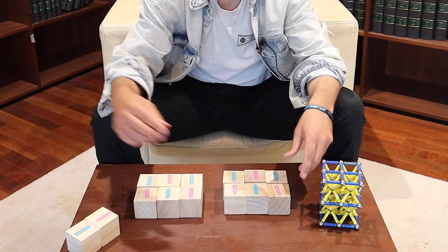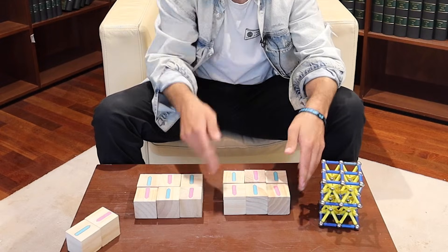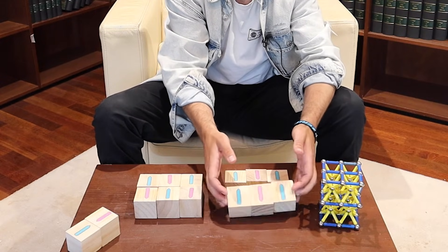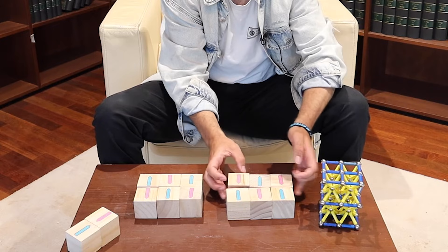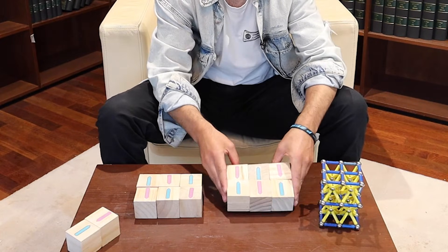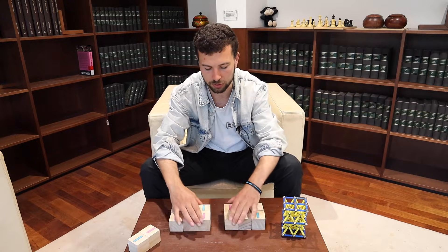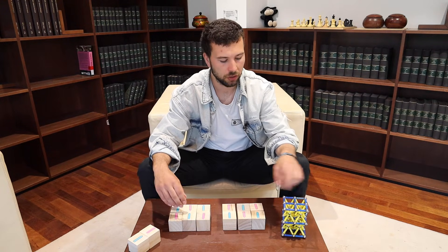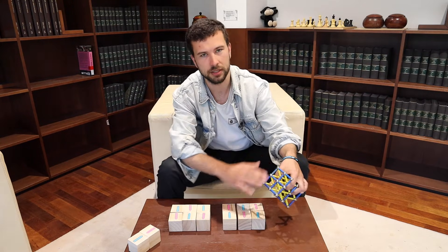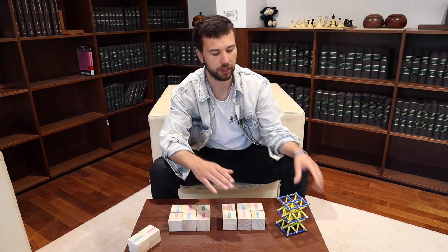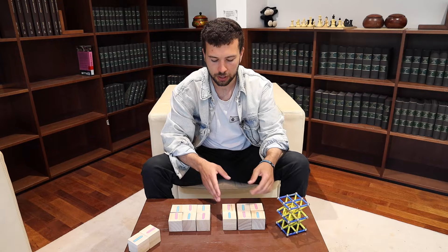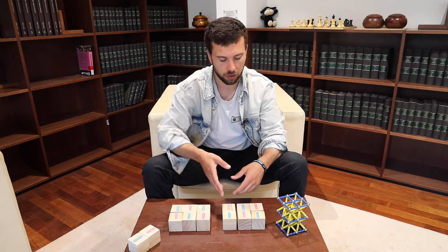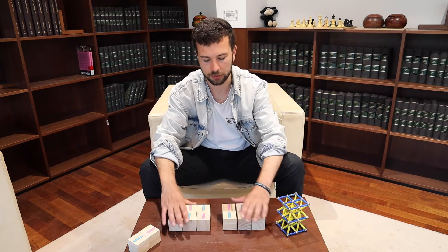We can sort this out in the material if all of the electrons on one side all flip together. Now they keep their nice anti-ferromagnetic alignment, and now at the boundary we're also still happy and they're free to hop around. When we take lots of electrons away from these layers in these cuprate materials, these lines where the holes all form up and we have these boundaries in this anti-ferromagnetic pattern happen periodically throughout the layer, forming what are called stripes.